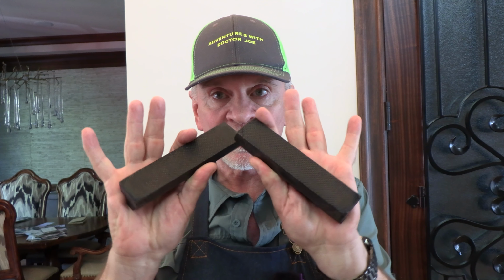So these are out of the oven, they've been tempered, so not only are they heat treated, but they're also a little bit stronger, less brittle. The reason we heat treated these is because when we skimmed the surface of this, we took that heat treated layer off. It was very hard metal, so we made them again very hard and then tempered them so they're not that brittle. They turned out really, really well. I'm excited to put these back in the vise and basically have it restored.